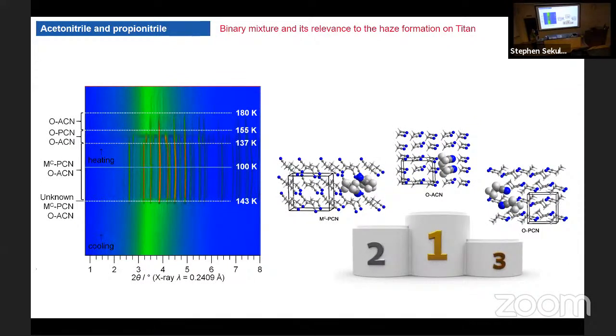When we have a mixture, we have really complicated behavior. First of all, if you remember, I said that acetonitrile is getting quenched when it's pure. For some reason, when it's mixed, that quenching doesn't occur. The high temperature form does not even exist. It goes directly to the low temperature form. On the other side, propionitrile is now quenched. Now we have the monoclinic form of propionitrile being quenched and the orthorhombic form of acetonitrile. When we are heating up the system, we have again an interplay of the phases.